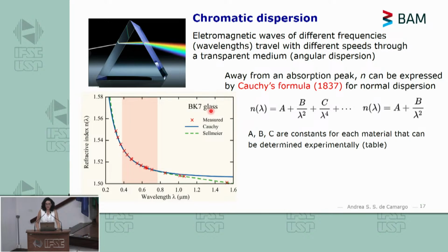We have for the BK7 glass, that's a crown glass from Schott. We have here in the visible region a very good agreement of measured results with the Cauchy formula that models the refractive index dispersion in the visible region, right? But you can see that in the UV and also in the infrared here, the matching is not so good anymore. So then this was further developed by Sellmeier.